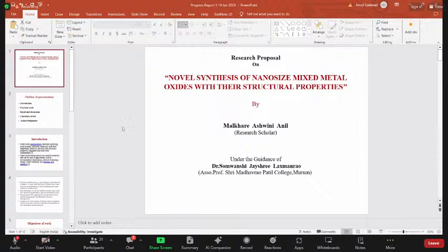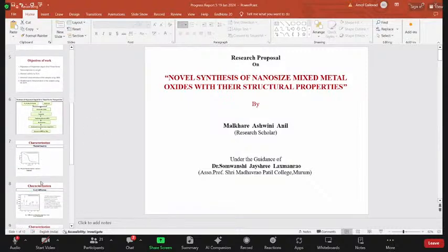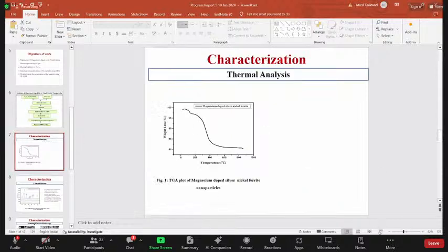Thank you. You go to your DTA TGA. Okay, sir. TGA graph. Yes, you show that. So here you are observing 2 points of decomposition. Yes, first one around 100, sir. 30 to 150, sir. Is it exothermic or endothermic weight loss? You are seeing the 2 weight losses here. Yes. Around 150. And then, sir, it is above 400. So at 150, you are observing one peak, whether it is exothermic weight loss or endothermic weight loss.